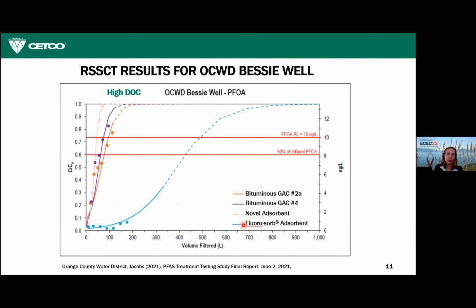And that's what this plot here shows. The C over C naught is a measure of the breakthrough, and the volume filtered is the volume that was treated before you hit your treatment target, which is 60% of the influent. This is for PFOA. You can see that Fluorosorb took the longest to break through under the high DOC condition, compared to GAC shown here, and so more water was treated before you would have to change out your media in a vessel, for example.